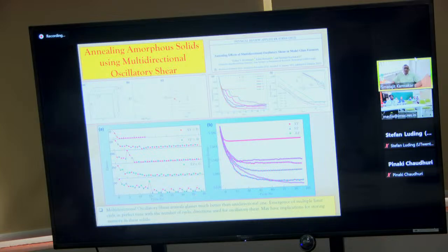So this figure schematically shows the average energy as a function of the oscillatory shear cycle. If you start with a poorly annealed glass, then you can anneal the sample very well up to a point, and after that it heals. And then there is an interesting energy scale. If you start your oscillatory shear below that energy scale, then it turns out that you can no longer anneal the sample using this oscillatory shear protocol.